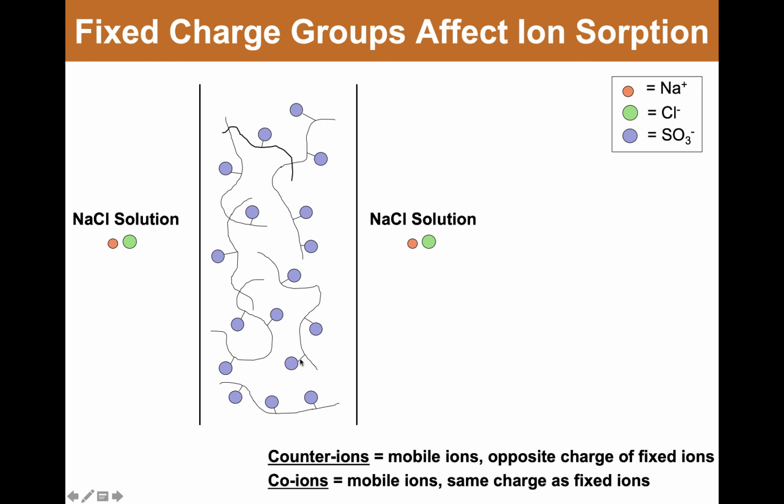And so what happens is, as you put this membrane into a salt solution like this, ion exchange will occur. So the membrane is hydrated, the ions are ionized and hydrated in the external solution, and by normal diffusion processes, the ions will start to migrate into and out of the membrane. The counter ions that are initially on this membrane can exchange out into solution, and over time, each of these negatively charged sulfonates will pick up a cation from solution, for example, a sodium ion, to remain electrically neutral.